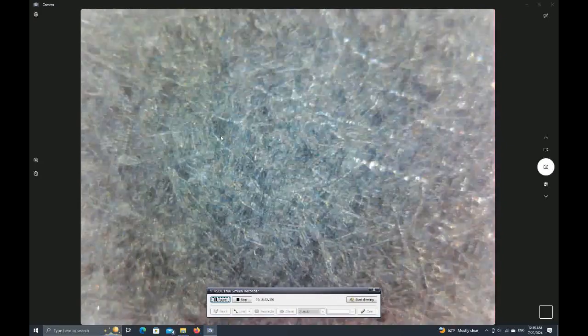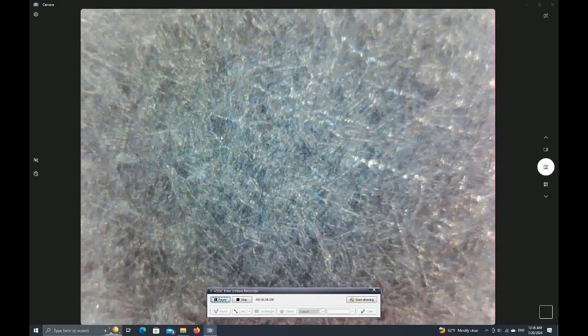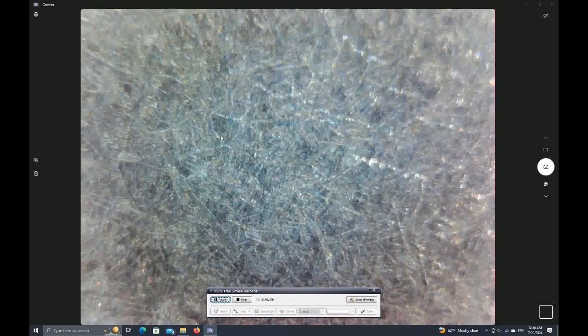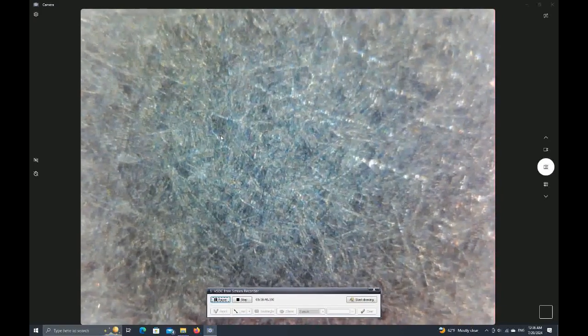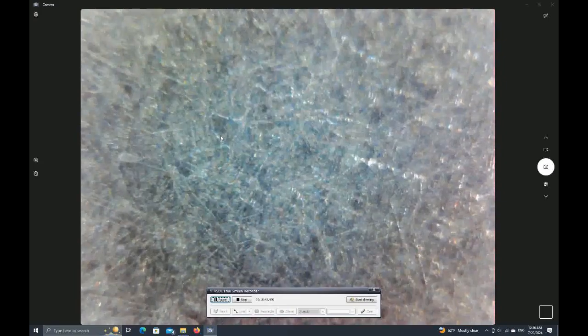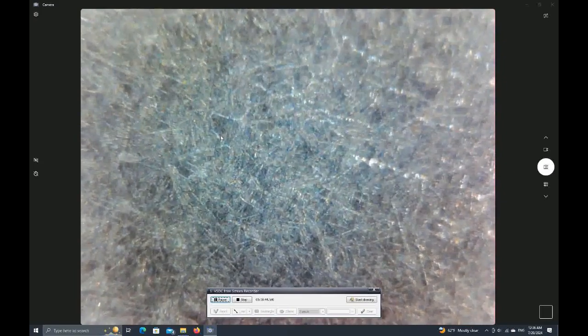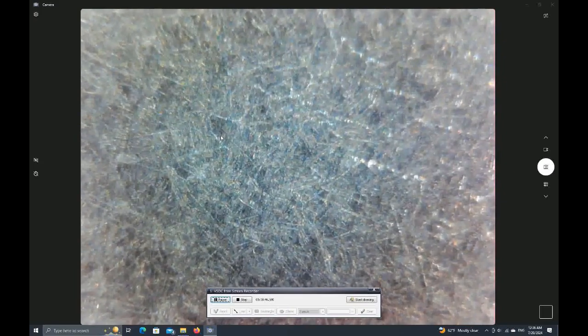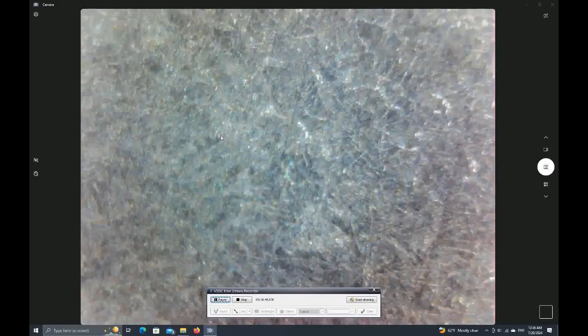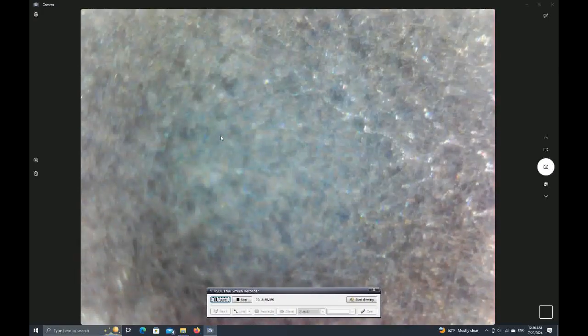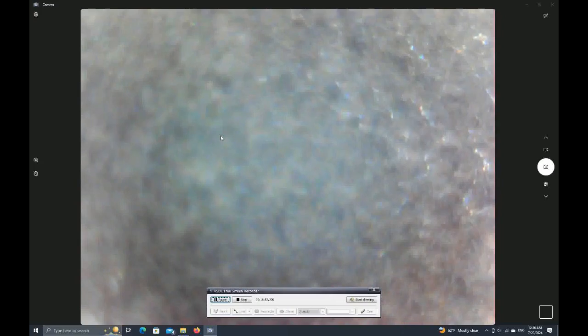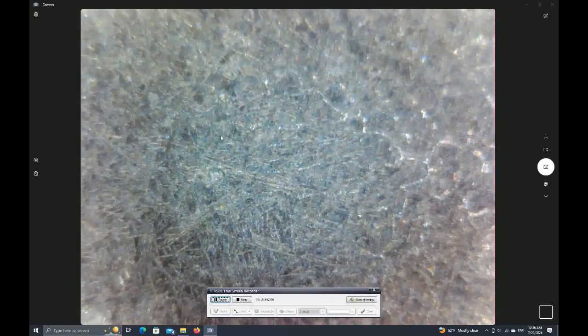It looks more disordered, in my opinion. It looks quite a bit more disordered than the one I made today. More chaotic. But they were otherwise made the same, so really the only difference here is that exposed region in the middle of the ingot that really changed things up in our end composition, apparently.